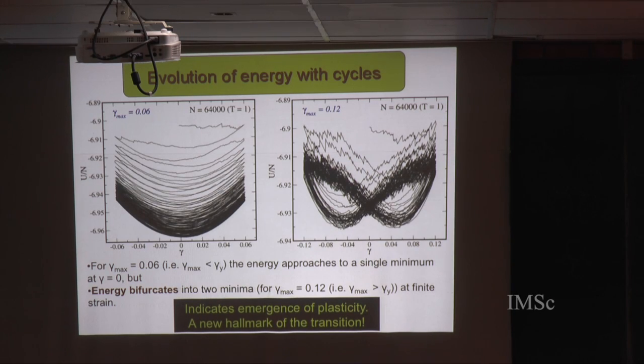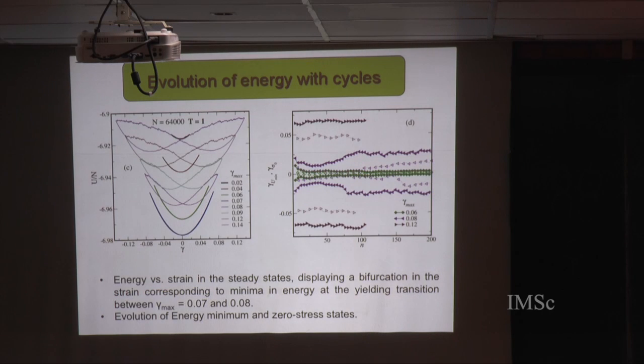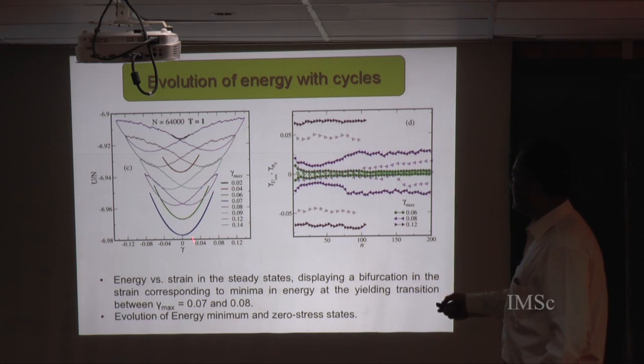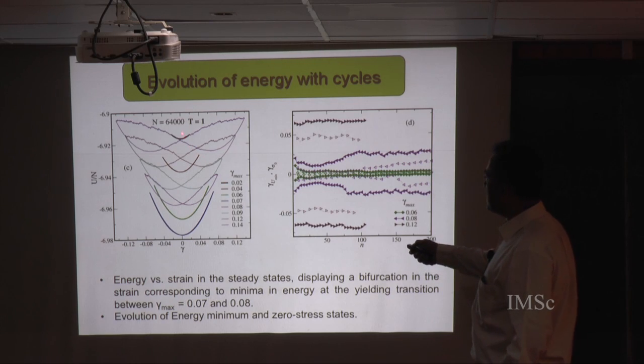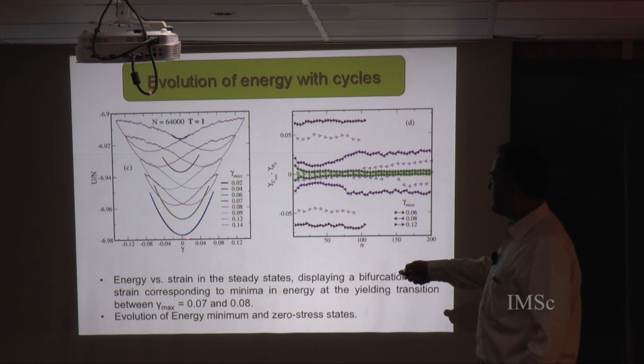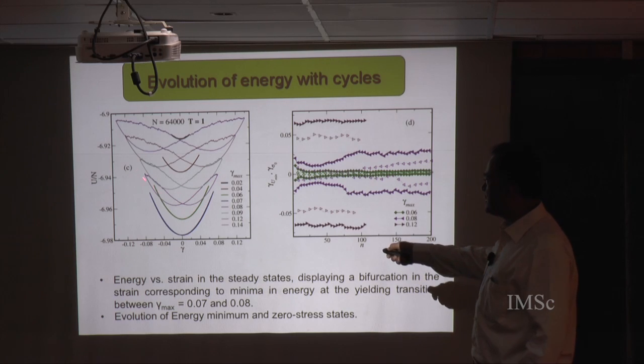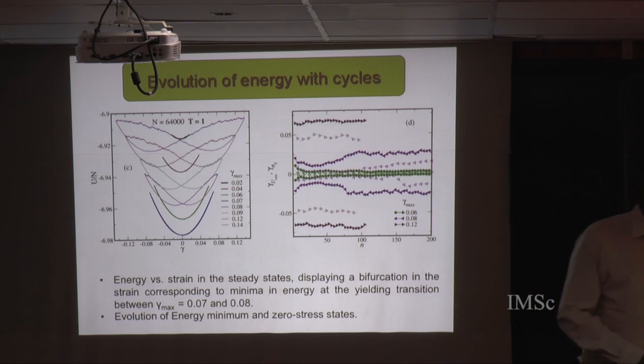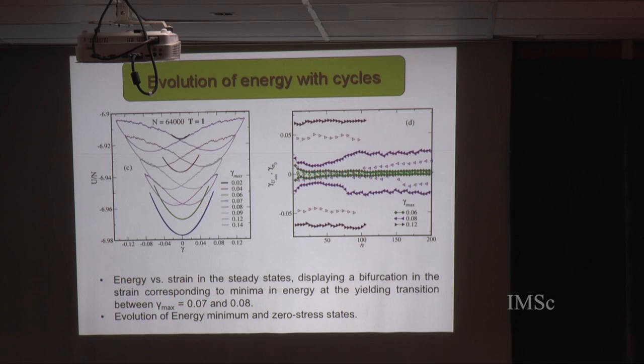Here is the cleaner version of this data. You start with energies for small amplitudes sitting in the steady state, and it goes down and down until you hit this transition, at which point the energies begin to go up and display this bifurcation, continuing to rise as you go to higher amplitudes of strain.